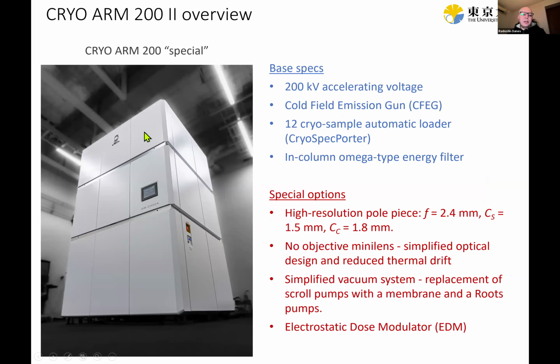Now, the machine we used for these tests is a JEOL CryoARM 200, which is now version 2. When we ordered it 3 years ago, it didn't yet have such a designation, so it was just a 200 kV cryo-EM, which we called special because we requested some modifications. So the base specs are 200 kilovolts, cold field emission gun. JEOL's machines are all with the cold field emission gun. It has a 12 sample autoloader and an in-column omega type energy filter. So the JEOL machines have an energy filter as standard.